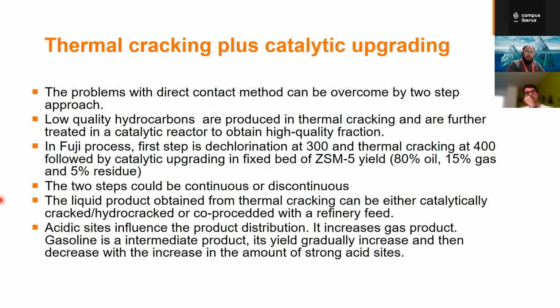One way of looking at it is also thermal cracking plus catalytic upgrading, what I told you also in one of the earlier slides, that you first crack the plastic in a thermal mode, and then you catalytically upgrade the vapors. This can overcome the problem of catalyst getting poisoned by some inorganic impurities, because when you thermally crack it, you can retain maybe solid impurities in a cyclone before you take the pyrolysis vapors into contact with the catalyst.